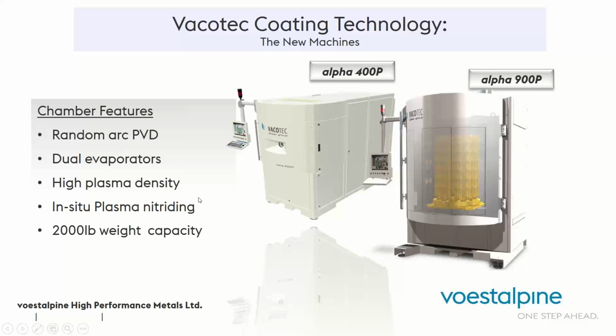One thing that we're proud to say is that we were the first ones to introduce in situ plasma nitriding prior to the deposition of the coating. This improves coating support and also provides additional cleaning in the cycle to prevent any sort of delamination or adhesion issues during the cycle. And it's something that's important to all of you.